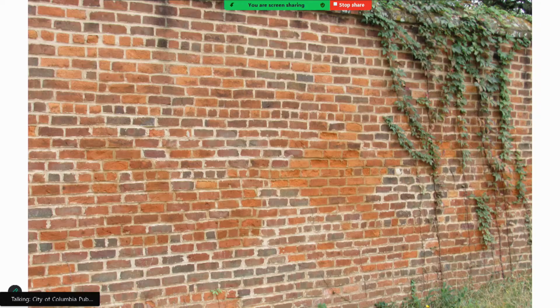And it's not necessarily anyone doing anything wrong. Sometimes I've seen it where bricks are just not good. They're soft. In this case, there probably have been some mortar patches that are not quite compatible with the brick. They trapped water. And so this is called spalling.